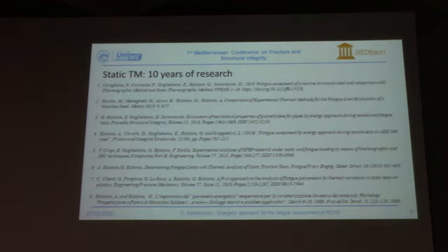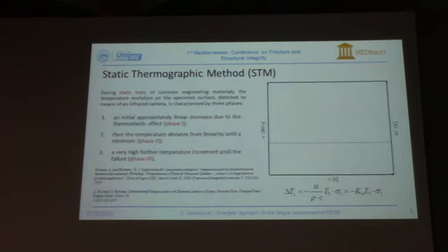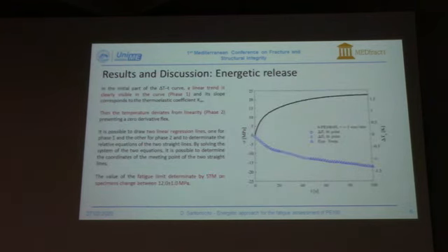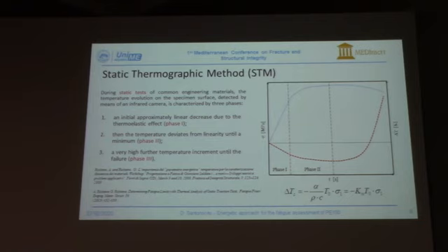Ten years ago, Risitano and Risitano proposed a novel procedure to assess the fatigue limit adopting a static tensile test. During a static tensile test, the surface temperature evolution exhibits three different phases. The first phase is an approximately linear decrease of the temperature due to the thermoelastic effect. The second phase is where the temperature deviates from linearity, and the third phase is where the temperature experiences a high further increment until the failure of the specimen.